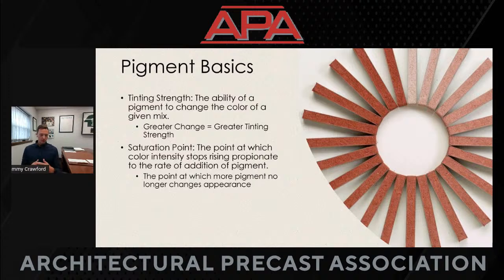Saturation point is the point at which color intensity stops rising proportionate to the addition of pigment. So if you look at this color wheel on the right hand side of the slide, right at about, I don't know, 7 or 8 o'clock, the color stops changing, and each strip in this wheel represents a 0.25% increase in addition. So there is some point where adding more pigment doesn't change the concrete anymore. And that's what's said to be the saturation point.